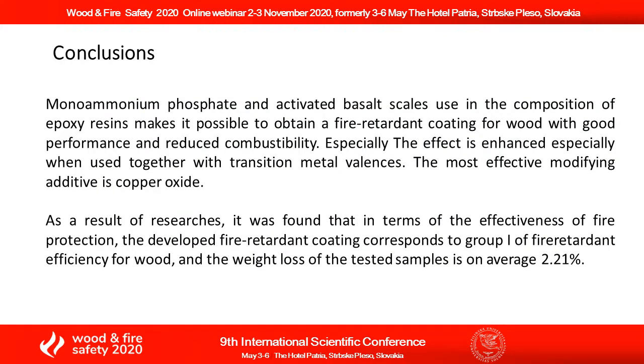Conclusions. Monoammonium phosphate and activated basalt scales used in the composition of epoxy resin make it possible to obtain a fire retardant coating for wood with good performance and reduced combustibility. The effect is enhanced especially when used together with transition metal valence oxides. The most effective modifying additive is copper oxide.